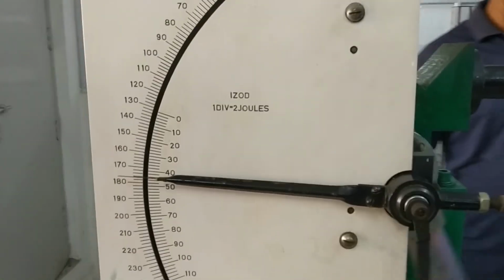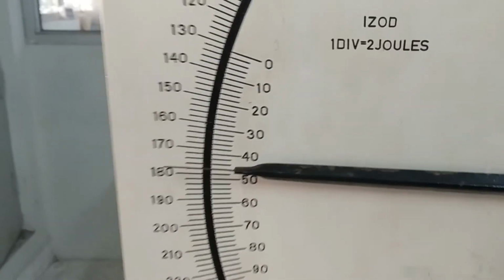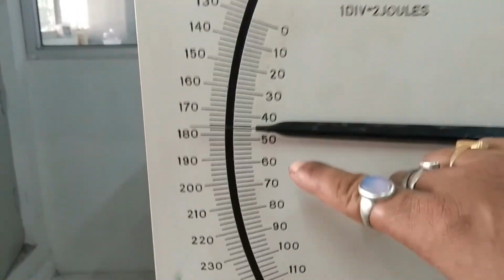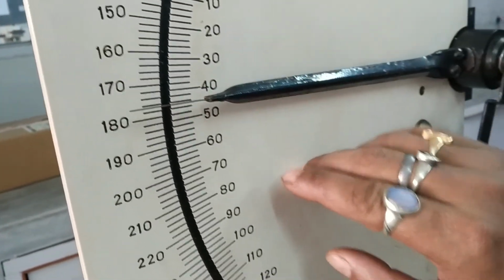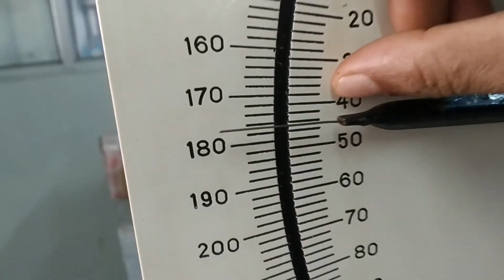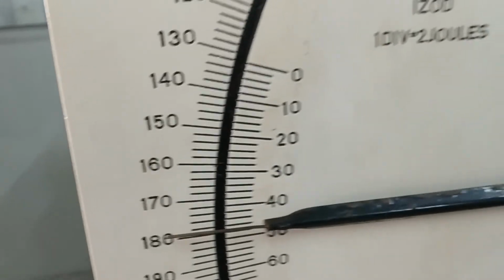So now we have seen the hammer impact the specimen, and the specimen failed. Specimen broke. So how much energy absorbed, that you can see directly from this dial gauge. The pointer is very clear, so clearly you see 40 joule, 42, around 44 joule. 44 joule energy absorbed. Now we will remove the specimen.